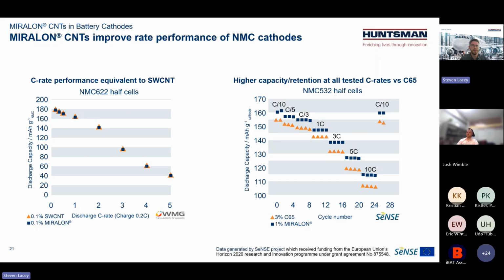Now, when we go to rate performance, we also had comparisons from third parties such as Warwick University and WMG, where they compared single-walled CNT at a very low loading of 0.1% to our MIRALON at the same loading, and we have identical rate performance. On the right side, you can see data from an EU Horizon 2020 project that we were a part of a few years back. It's called SENSE, that we're very proud to be a part of. We also had very nice data on different C rates, and across all C rates up to 10C, we have noticeably higher capacity using 1/3 of the conductive additive.